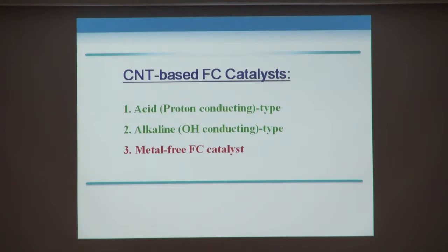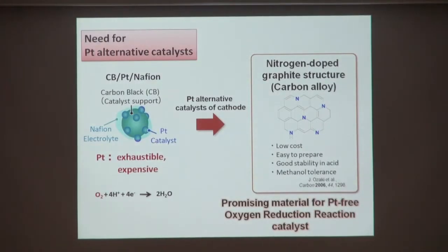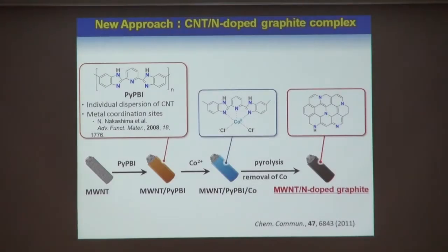So now maybe I show a little bit about the metal-free fuel cell catalyst. Here is our composite, carbon nanotube PBI composite. And after coordination of cobalt ion, we heat it, pyrolysis or calcination at a given temperature. Then we can obtain carbon nanotube nitrogen doped graphite like this. And the structure may be like this.